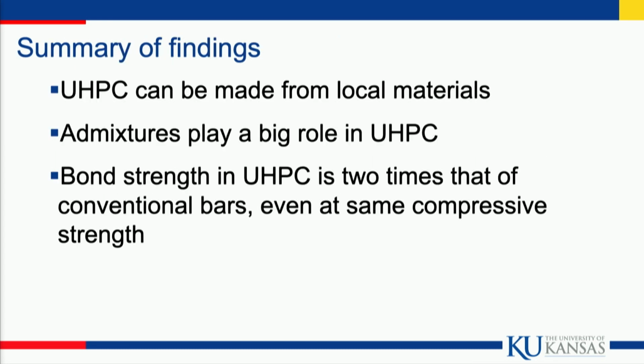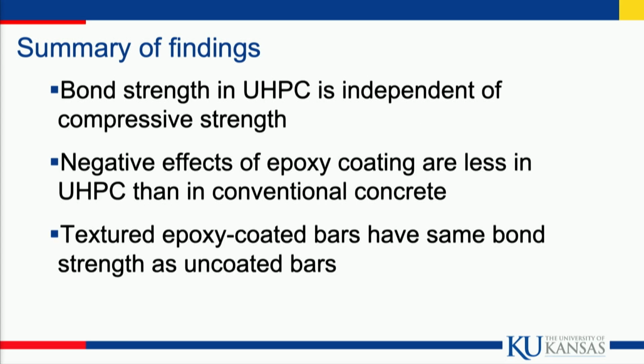Summary: UHPC can be made from local materials here in Oklahoma. Admixtures play a big role. You've got to pick the right ones. Bond strength is 2 times what you get with conventional bars, even at the same compressive strength. Bond strength in UHPC is independent of local variations in compressive strength. We saw that in our tests. The negative effects of epoxy coating are less in UHPC than in conventional concrete. And textured epoxy-coated bars have the same bond strength as uncoated bars.